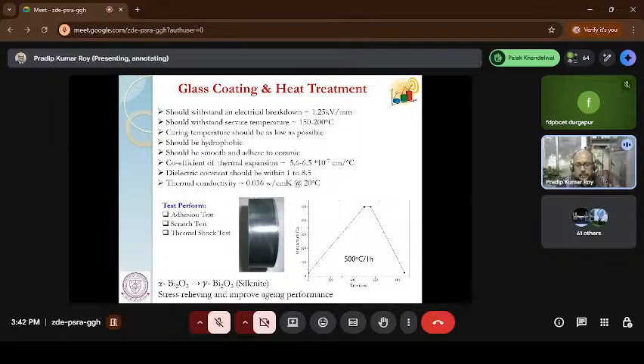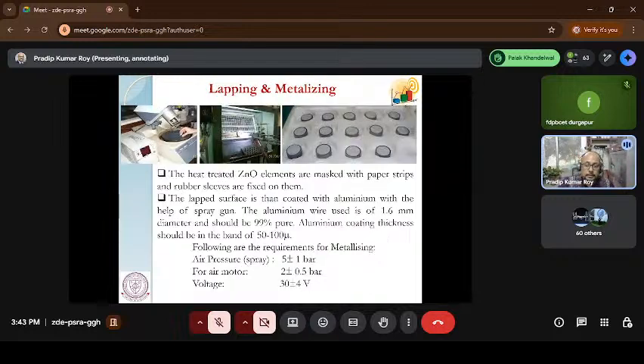So you need certain properties when I do this insulation. For example, the breakdown voltage should be around 1.25 kilovolt per mm. It can withstand temperatures of more than 200 degrees Celsius. It should be completely hydrophobic. It should adhere very well with the ceramic block. It should have very low thermal expansion. It has a good dielectric constant of around 8.5, and thermal conductivity should be as low as possible, because I said it's a purely insulator material. There should not be any kind of leakage, defects or flaws around the block. Otherwise, there is a chance of flashover around the side of the block when the surge comes.